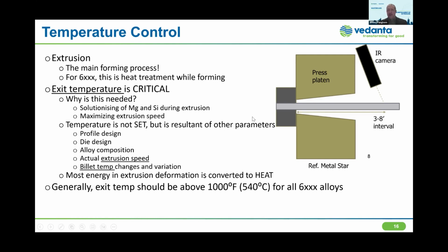Remember that we have a very massive hydraulic cylinder, thousands of tons of force. Most of that force, that energy, is being converted into heat. So there is a lot of heat generation in the process. For example, if we're typically running a billet at, I think in Fahrenheit more, but let's say it's at 470 Celsius, we may see an exit temperature of 520 Celsius, meaning we actually heated our metal up 50 degrees Celsius during the extrusion process. That would be fairly typical.